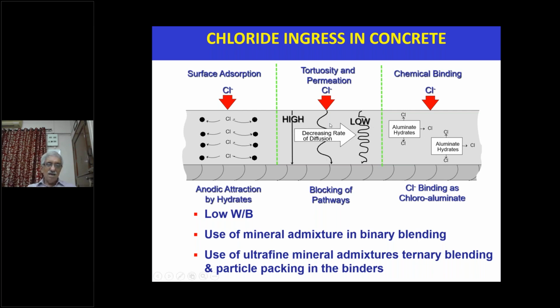It is like the pores will be having tortuosity, and with the proper packing or with the proper mixing of the binders, it will have more tortuosity, so the water, or the chlorides, will take a longer time to reach the steel. And the last is ultrafine mineral admixtures, ternary blending, particle packing in the binders also is taken care of. Then it will have a very complex way of chlorides going to the steel, and the route will be much longer, and by the time the concrete will harden and therefore prevent any sort of attack of chlorides on the steel.